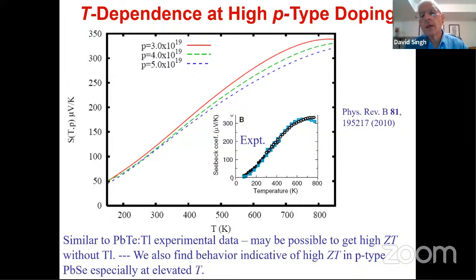And so that also has an effect on the Seebeck coefficient, which we can calculate. I told you we can calculate as a function of temperature. So this is temperature. And this is the value of the Seebeck coefficient. And it depends on the number of holes, in other words, the doping level, as we discussed. And so these are 3 different curves corresponding to 3 different doping levels in units of holes per centimeter cubed. And so what you see is that the curves are fairly close and they have a certain shape. They increase with temperature, which is quite normal.